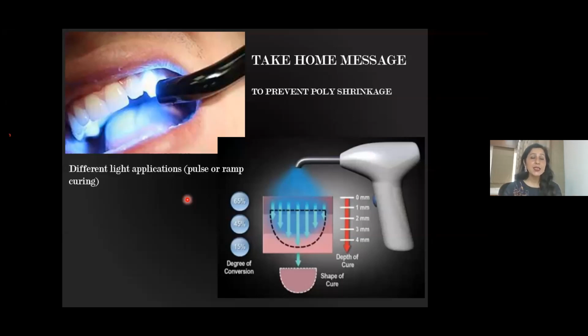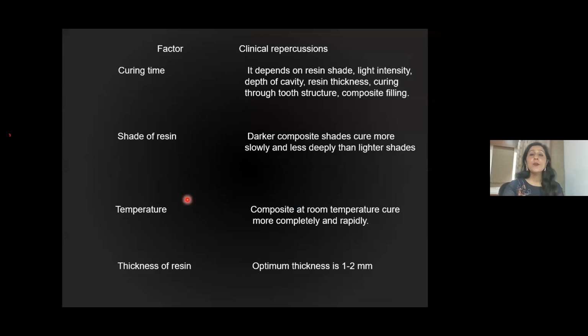And then after that, you can increase the light intensity and do the rest of the monomer conversion to polymer. So this is a very good phenomenon, and to date, the most acceptable light curing phenomenon. And you have this phenomenon in your light cure machines. If you have a good light cure machine, then you do have this. So just a recapitulation: curing time depends on resin shade. The darker composites need more curing time, lighter shades require less curing time.